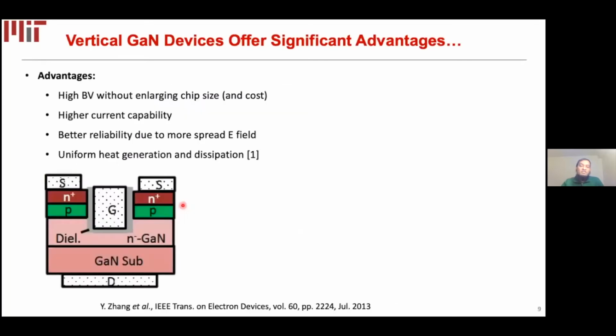Now, we can solve this problem by going vertical. The primary advantage of the vertical geometry is that we can achieve very high breakdown voltage without enlarging chip size, because now we can increase the drift region, which is along the vertical direction, by just controlling the thickness of the epi layer instead of the device footprint. Also, we can play with the geometry and achieve much higher current capability without having to impact the footprint of the device. And vertical geometry also helps with better distribution of the electric field and uniform heat generation.